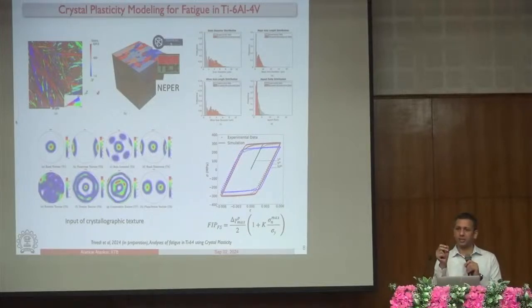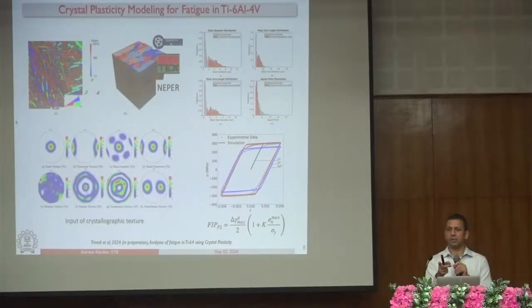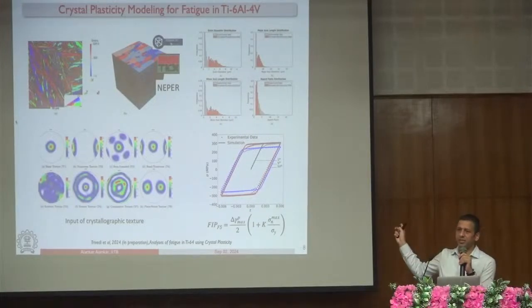This texture thing is very important because texture represents how statistically grains are oriented in that polycrystal. And that orientation plays a big role on the overall mechanical deformation, right? So the model does a very good job. It can capture the stress-strain cycles that you see in experiment, and we can run it for a very large number of cycles. However, now the challenge is that this particular simulation had about 30,000 elements, right? And each simulation used to take about a day, which is a cheap simulation, by the way. A day of a simulation like this, crystal plasticity finite element, is not a big deal.